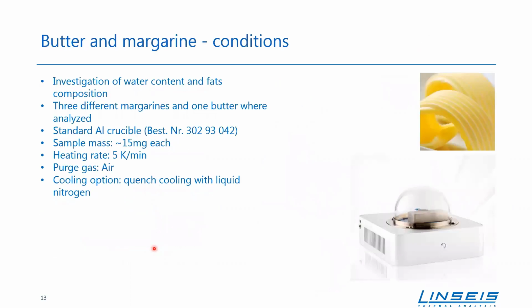So maybe let's start with some investigations. I want to show you what's possible with the ChipDSC, and maybe you get some ideas what you can use this DSC for. We started with butter and margarine. For the measurement conditions, we used the ChipDSC 10. What we want to know is, what about water content and the fats composition? Is it possible to separate them clearly or not? For this reason, we bought 3 different margarines and a butter and measured all of them in our aluminum standard crucible. The sample mass was more or less 15 milligrams for each, at a quite low heating rate of 5 Kelvin per minute.